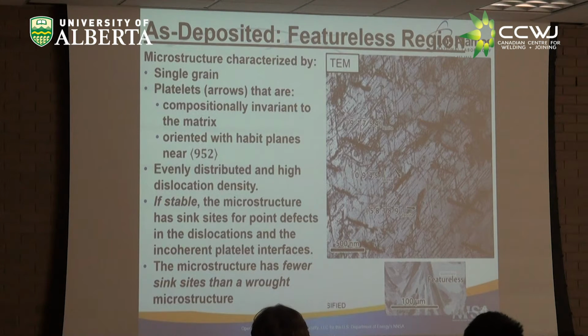So in the TEM analysis we looked at, here's those 952. We saw these funny platelets that are shown here, right? And you can see them, these platelets here are at 90 degrees to each other. The young man who did this was a postdoc at the time, and I asked him to tell me what zone axis we were on, and he never did. He found that the plates were oriented relative to the matrix with a habit plane of 952. And he said, oh, this is one of the orientation relationships you find in high carbon steels, the habit plane. And I had to break his heart by telling him that a habit plane of 952 is between the martensite and the austenite, and this is ferrite.